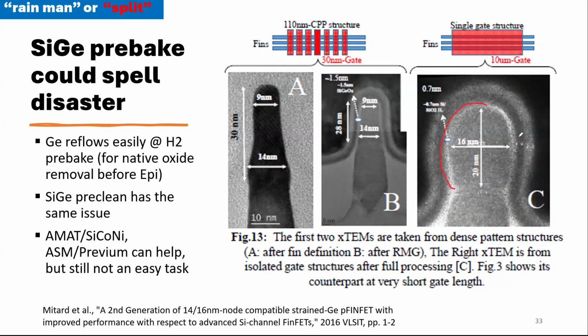It will reflow to become a big ball. It will deform the shape because germanium reflows easily. You need to remove the native oxide from the germanium, but that pre-bake is a hydrogen pre-bake. Hydrogen pre-bake will make this germanium or silicon germanium like a ball. The reason is that it will increase the mobility of the atomic surface diffusion of the material. So you have to use SiCoNi and ASM Previum, but it's not an easy task. That's my conclusion.